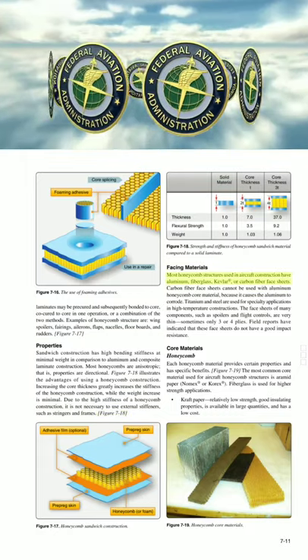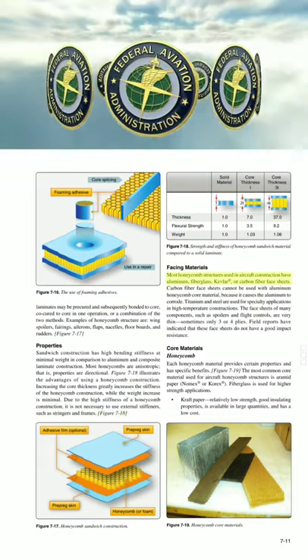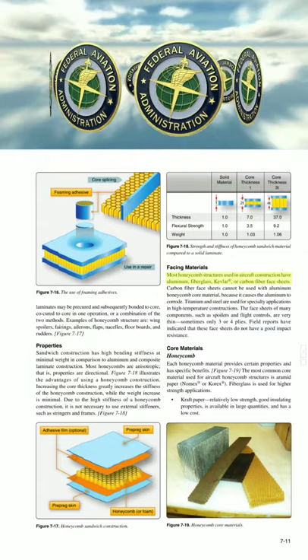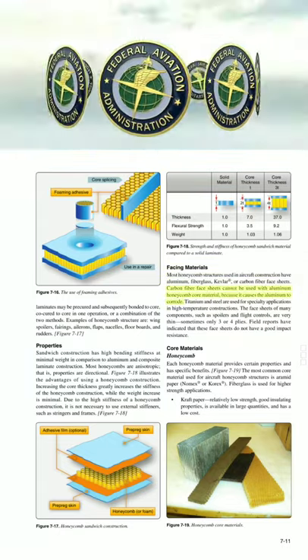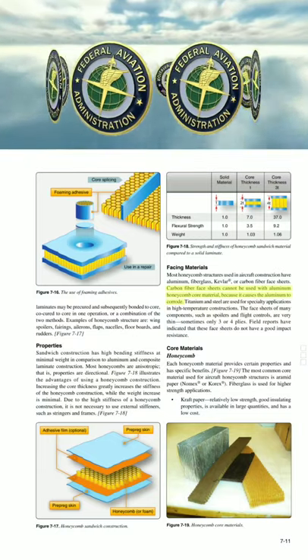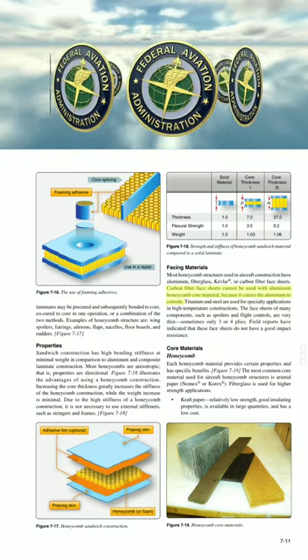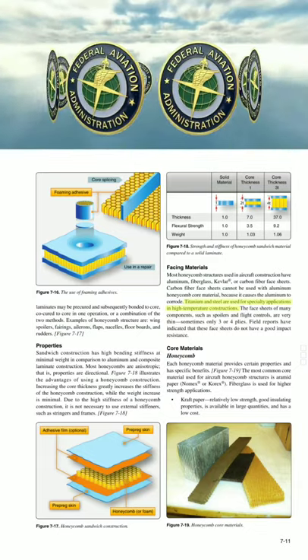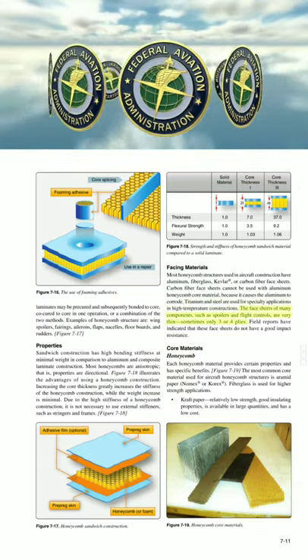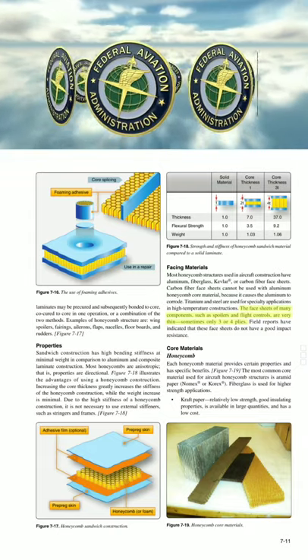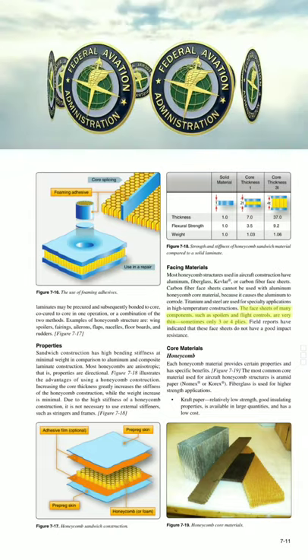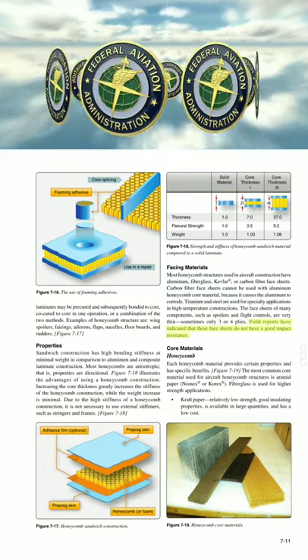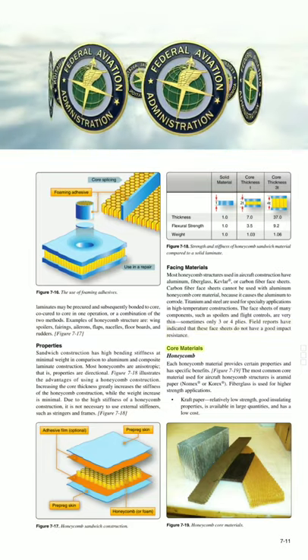Facing materials. Most honeycomb structures used in aircraft construction have aluminum, fiberglass, Kevlar®, or carbon fiber face sheets. Carbon fiber face sheets cannot be used with aluminum honeycomb core material because it causes the aluminum to corrode. Titanium and steel are used for specialty applications and high-temperature constructions. The face sheets of many components such as spoilers and flight controls are very thin — sometimes only three or four plies — and field reports indicate that these face sheets do not have good impact resistance.